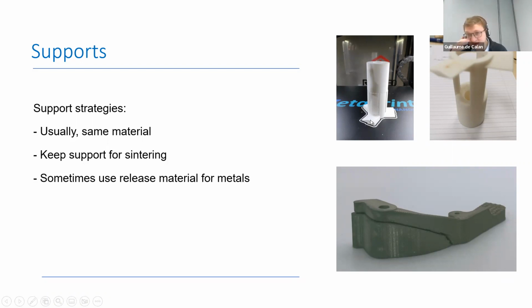It removed lots of supports, of course, but that meant you had a quite massive zone here on top of the print, and if you don't want any deformation during sintering, you should keep the supports for sintering. Again, they are relatively easy to remove afterwards. We just use a screwdriver and remove them in a matter of a minute. That was really very easy. But we did keep those supports, the big ones here, and also the ones below the small elements there.